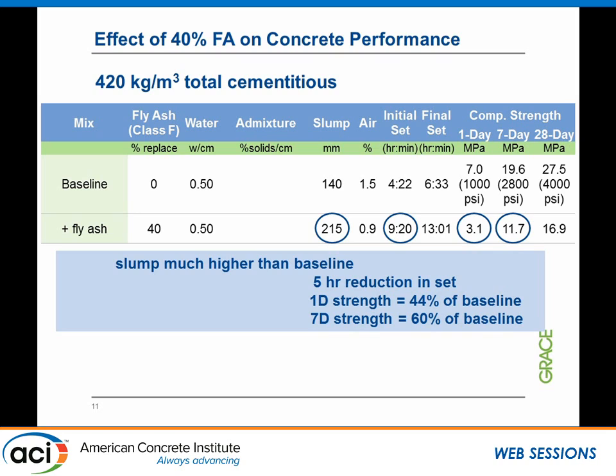So in this case, we have a baseline that has a slump of about 6 inches, set time and compressive strength. When we added the fly ash at 40% replacement level, yes, we saw an increase in slump by about 3 inches, but so does the initial set, right? Now you're increased by 5 hours, which is really not something that we can use in the field, and the strength decreased by half.